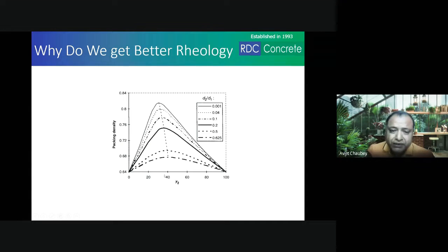So in this study, D2 by D1 is the ratio of the smaller size aggregate to the bigger size aggregate. So 0.625. If let us say 20 was the size of the bigger aggregate, then the size of the smaller aggregate is 12.5. So he makes 20 aggregate and 12.5 aggregate at different percentages of ratio. So 20% of 20 and 80% of 12.5 aggregate, and that gave this much particle packing. At 40% it gave this much. So this mixture, at different percentages from 0 to 100, means the percentage of 20. As you keep on going from left to right, the percentage of 20 is increasing, right?